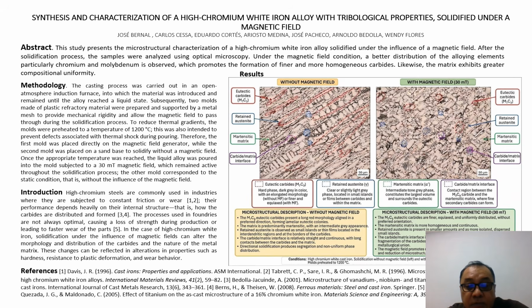Retained austenite is observed as small islands of a dim field located in the interdendritic regions and at the border of the carbides. The carbide-matrix interface is relatively straight and continuous, with long contacts between the carbides and the matrix. Directional solidification produces segregation and non-uniform phase distribution.